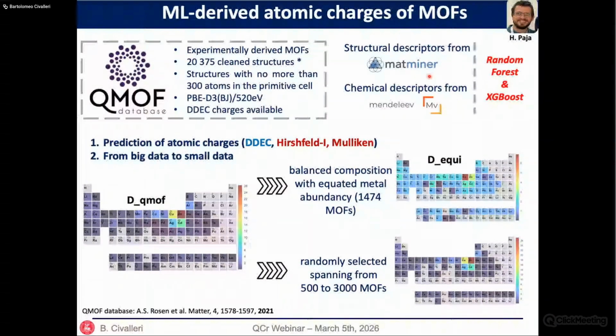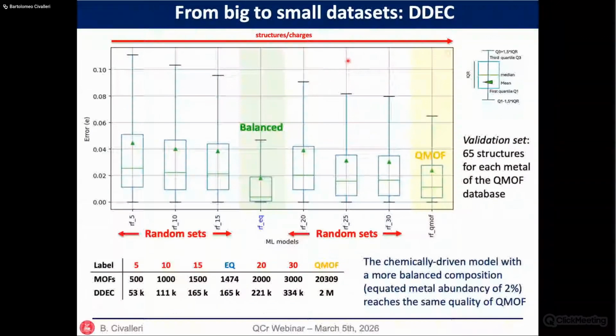So then we predict the charges of the atoms through random forest or XGBoost with different chemical descriptors. And these are the results comparing the randomly selected data set with this chemically balanced data set and the whole QMOF data set, for a validation set of 65 MOF structures. As you can see, this triangle is the mean error. And you see that this chemically balanced data set allows us to arrive at a very nice agreement with the whole data set of QMOF.